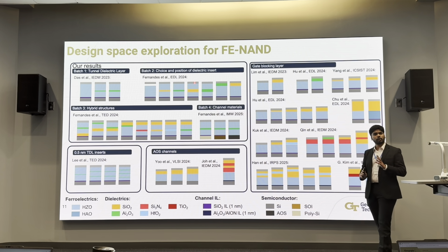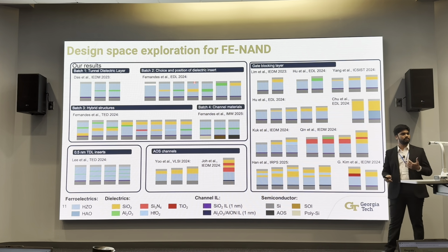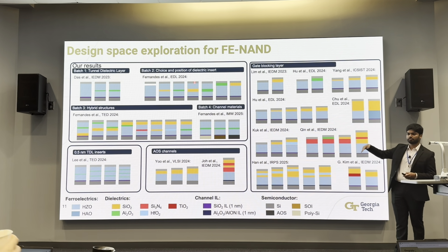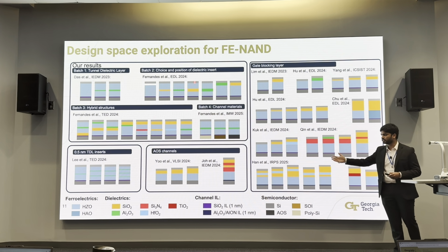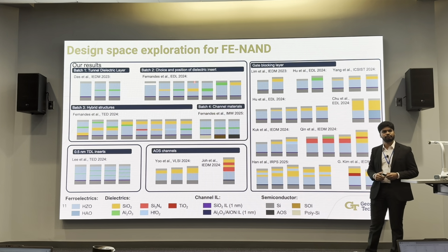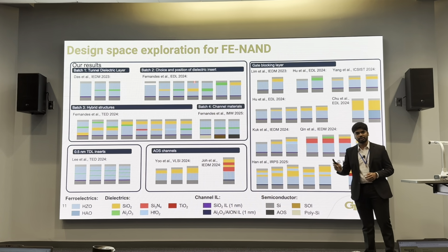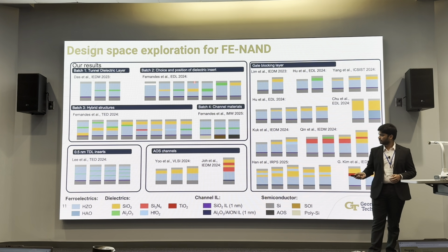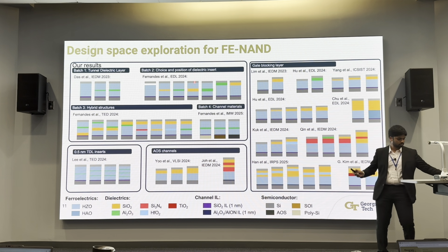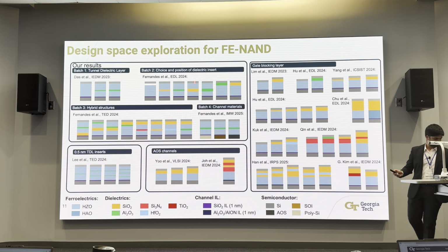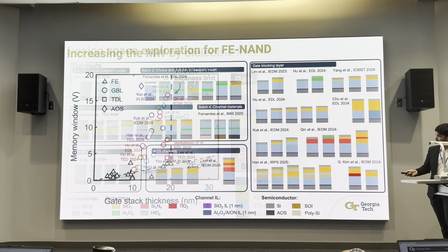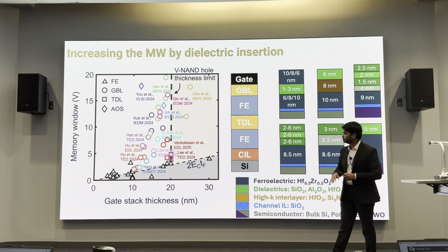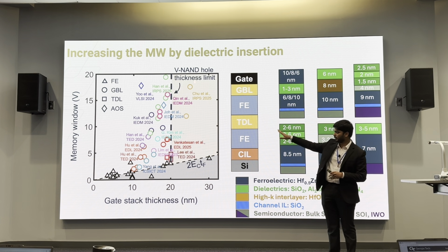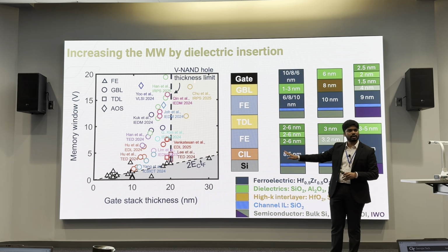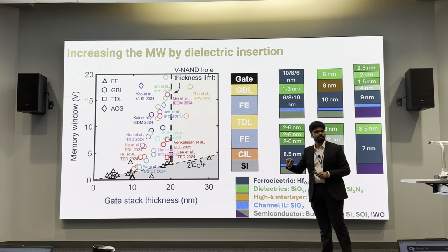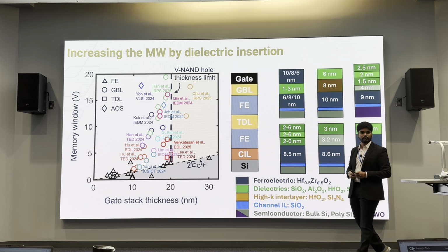Here's a quick snapshot of what the industry and academia have done over the last 2 years. Different combinations of materials, ranging from channels, ILs, and different dielectrics, and even different compositions of ferroelectric materials, to engineer the memory window. To make it easier to digest, here's a map of the memory window versus the gate stack thicknesses, and a maximum of 19.4 volts was demonstrated back in IRPS 2025 earlier this year.